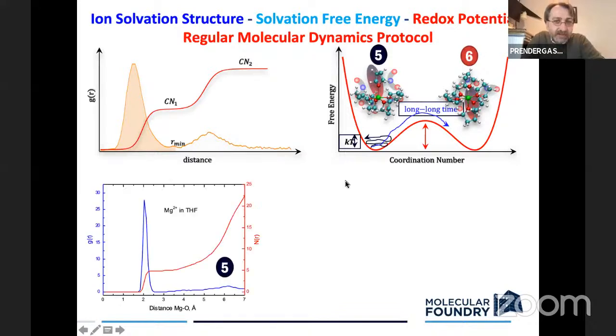Okay, so we looked at magnesium on its own in the THF solvent, and we found that if you began a simulation in 5-fold coordination, it was long-lived enough that you could get very good statistics on its G of R. It's a radial distribution function. So the coordination between magnesium and oxygen, and the associated coordination number. And it's very clearly 5, no deviation.